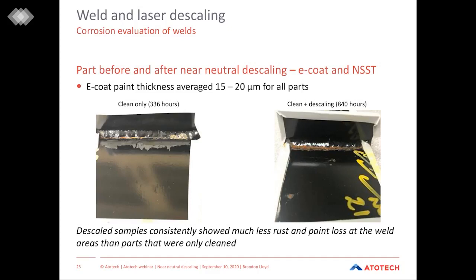Talking about some of the corrosion evaluations of welds. So this particular study was on parts before and after near neutral descaling, and they were e-coated and then submitted for neutral salt spray evaluations. The e-coat paint thickness on these parts was about 15 to 20 microns. So the image on the left you can see is a part that was cleaned only and was submitted to neutral salt spray for only 336 hours. The part on the right is clean and descaling, tested up to 840 hours.